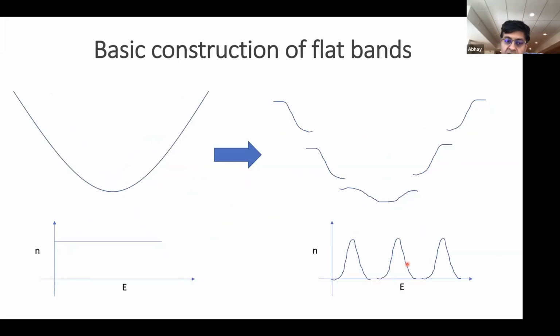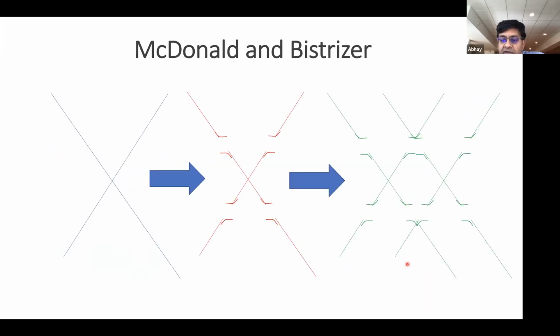Okay, so if you now get into the details of individual materials, the details are slightly more complex than this and often can be very interesting. Let me walk you through the most famous of these examples, which is the case of twisted bilayer graphene. So in graphene, you have the famous Dirac dispersion for a single layer. If you follow exactly the same argument that I gave you on the last slide, then this would say that once you have a periodic potential, this periodic potential is going to open subbands in graphene, and these subbands are going to be spaced by the wavelength of your